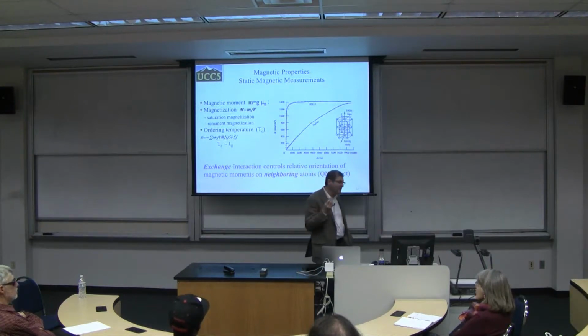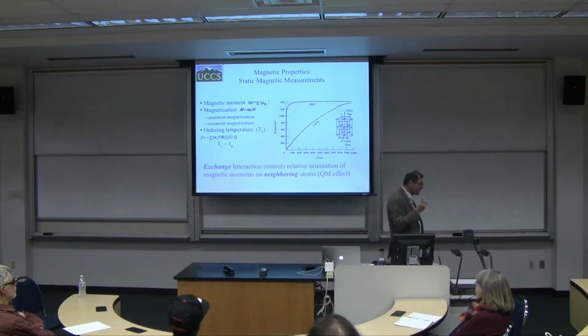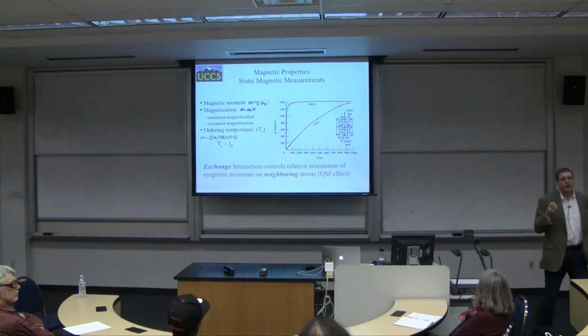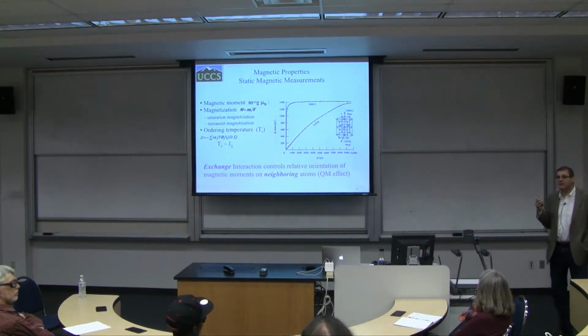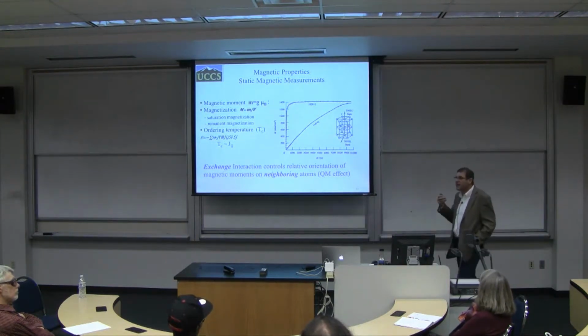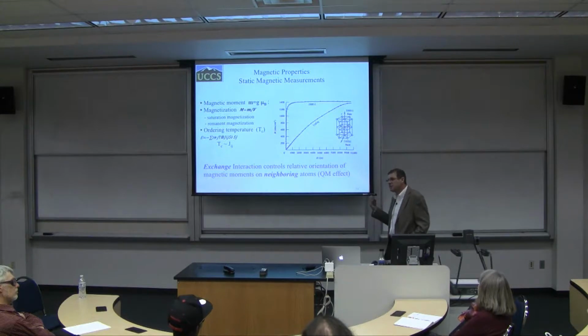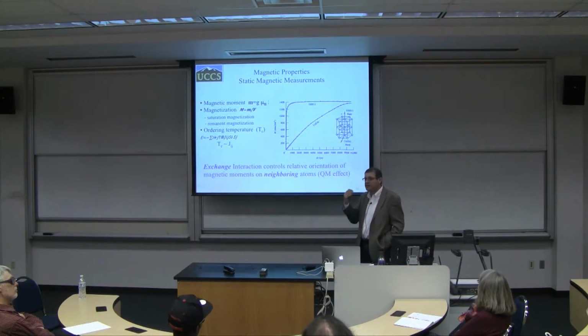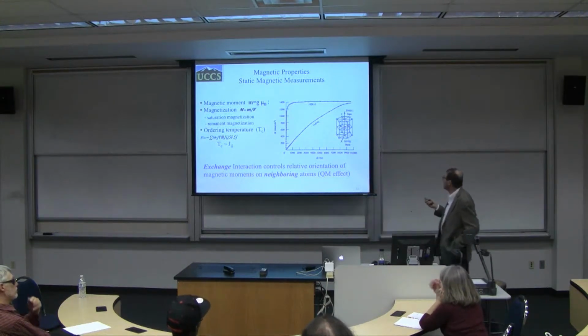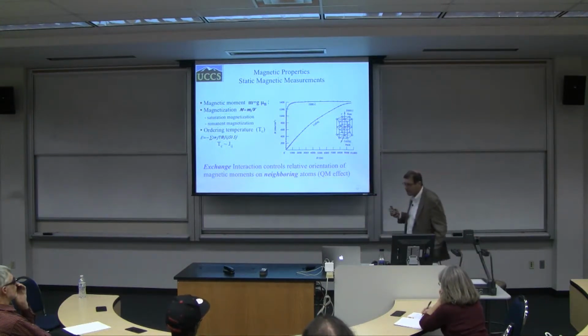Now, if you think about it, magnetic materials are the only place where you can see quantum mechanics and relativity at the same time. What determines this difference is anisotropy, and this is associated with the fact that electrons orbit around the nuclei, and there is a coupling between spin and this orbital motion. This is what basically influences your anisotropy. Okay, let's move on.